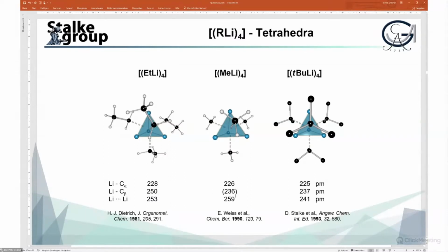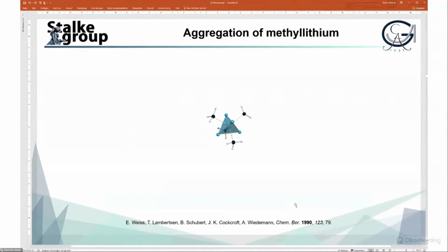I filed the distance in methyllithium. This is something awkward because there is no C-beta in methyllithium, but this is the coordination in methyllithium determined by Erwin Weiss and Cockcroft by powder neutron data. They located the hydrogen atom positions, and they are staggered to the lithiums and not eclipsed.